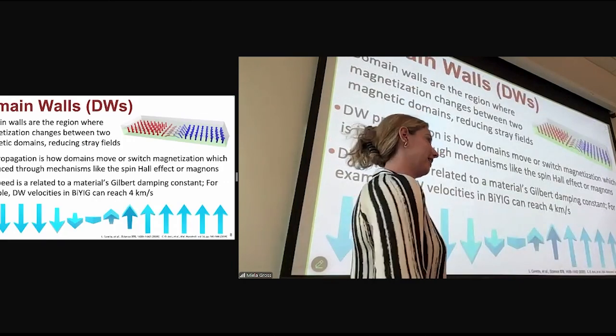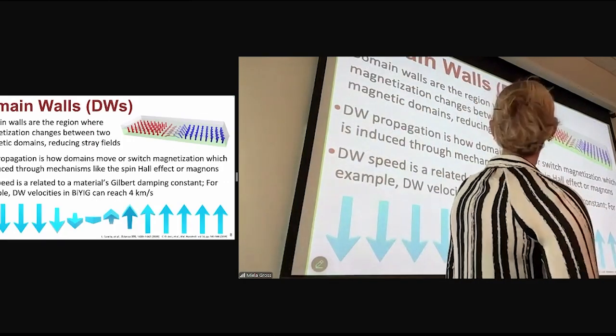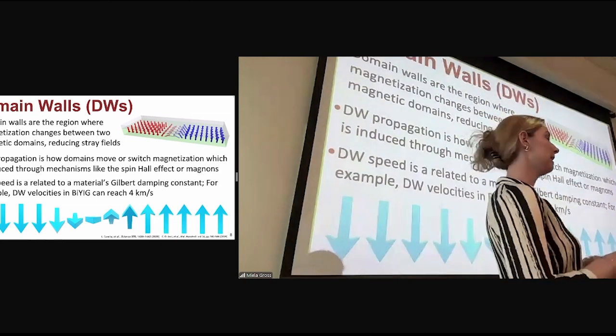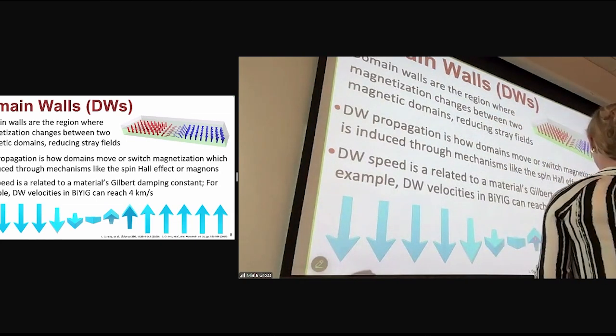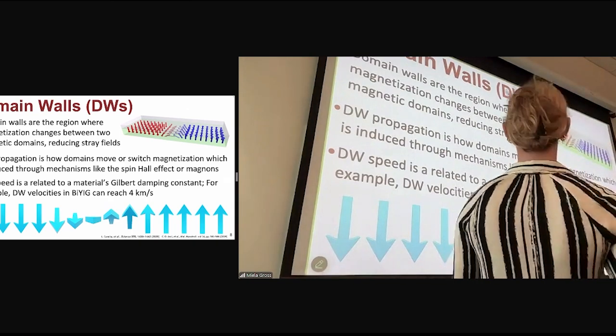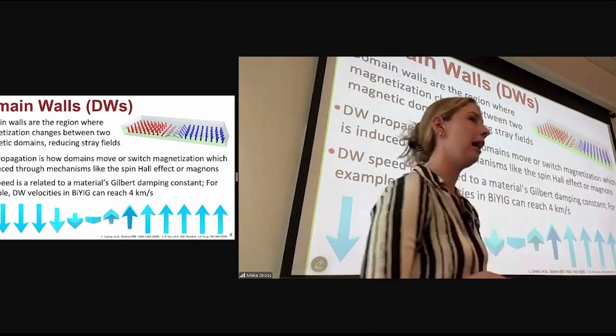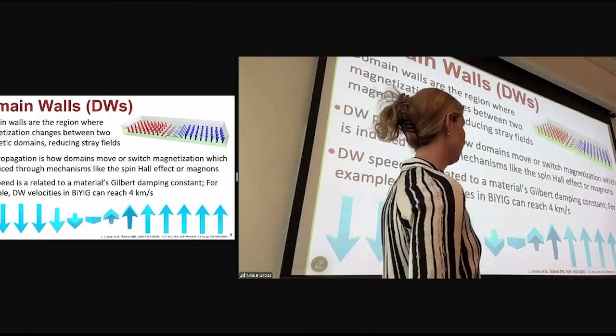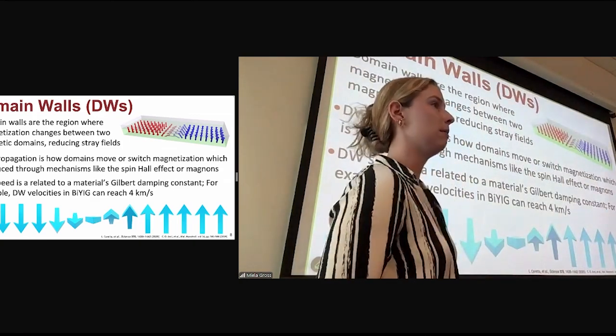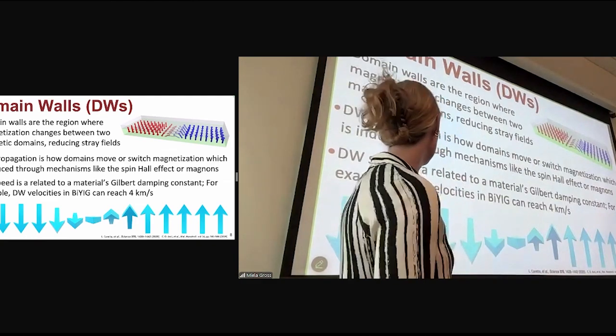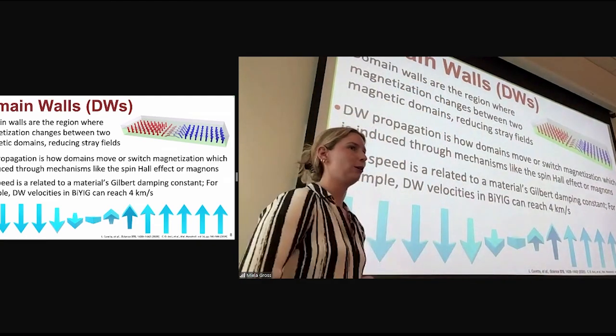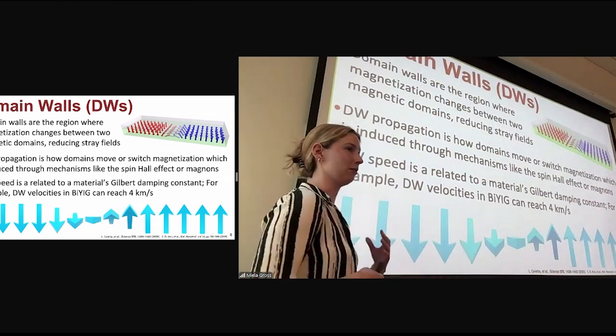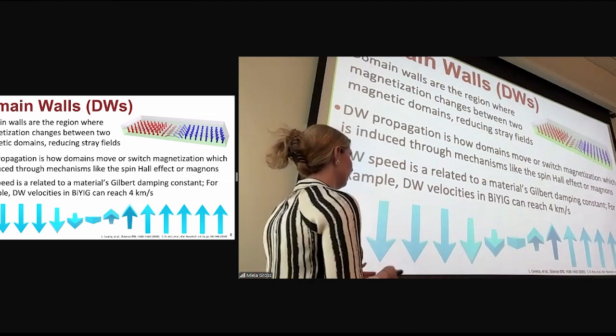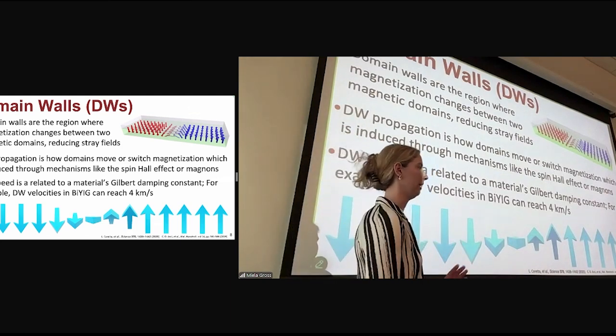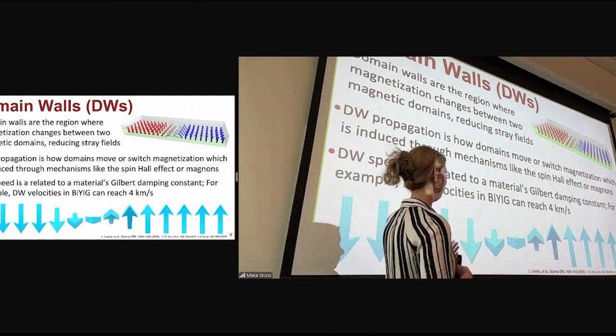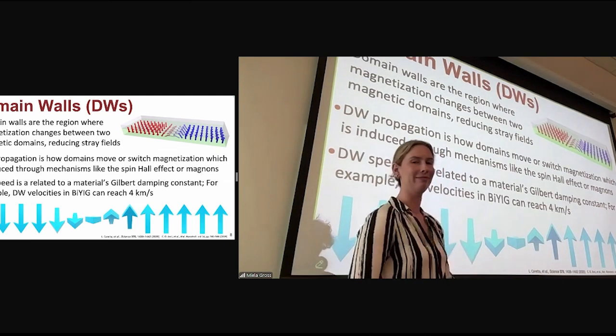Okay, our next ingredient here are domain walls. Domain walls are the region where the magnetization changes between two domains, showcased here in this little picture, and then here in this little diagram below. Domain wall propagation is how domains switch or magnetization moves, and they're induced through mechanisms like spin Hall effect or magnons, for example. The speed of this domain wall propagation is inherent to a material's Gilbert damping constant. So, for example, bismuth substituted yttrium iron garnet, which I'll mention later on, has reported domain wall velocities that can reach 4 kilometers per second.